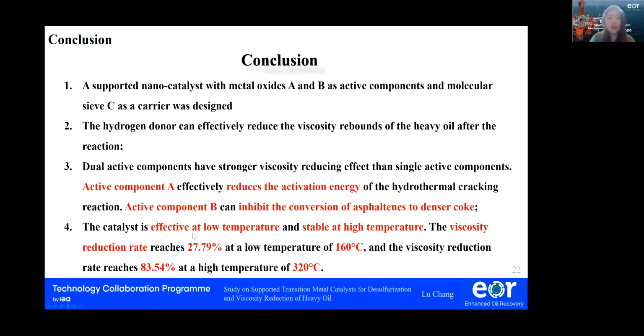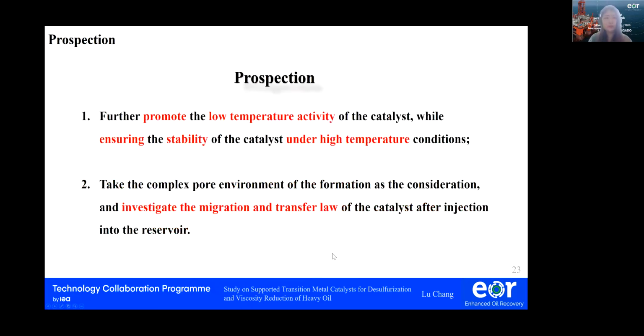The catalyst is effective at low temperature and stable at high temperature. The viscosity reduction rate reaches nearly 30% at a low temperature of 160 degrees, and reaches over 80% at a high temperature of 320 degrees. In the future, we would like to further promote the low temperature activity of the catalyst while ensuring the stability of the catalyst under high temperature conditions.